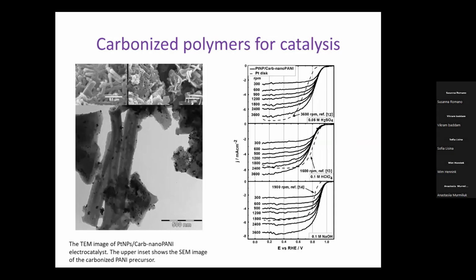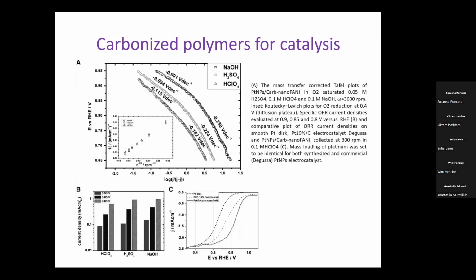final example where we use these carbonized polymers, carbonized Pani, as a support for platinum-based nanocatalyst for fuel cells applications. So you can see here at the TEM that we have this nice morphology of carbonized Pani nanotubes. And in contrast to just carbonized Pani, which is active for oxygen reduction reaction in alkaline media, and if someone says that carbons are active for oxygen reduction in acidic media, I would be very suspicious. In this case, you see that this catalyst, which has platinum nanoparticles, is now active in acidic media and in alkaline media for oxygen reduction. So we can choose different fuel cell technologies for the application of such a catalyst.